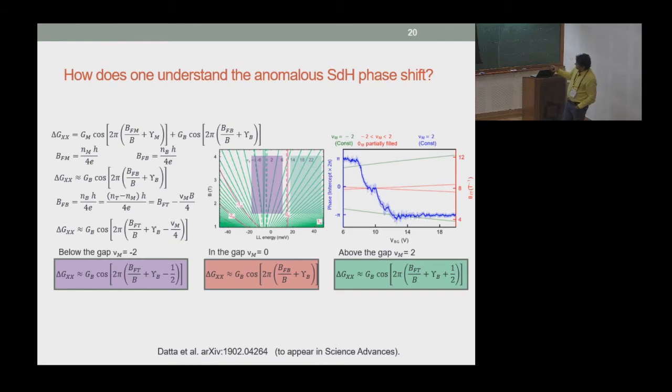So what we experimentally did was basically map out this anomalous phase as you move through the Fermi energy, and, as I kind of alluded to, you move from pi to minus pi, and precisely when the monolayer band or the Dirac band is gapped out, the Berry phase goes to zero. This is kind of consistent. So I think this is the essence of the story.